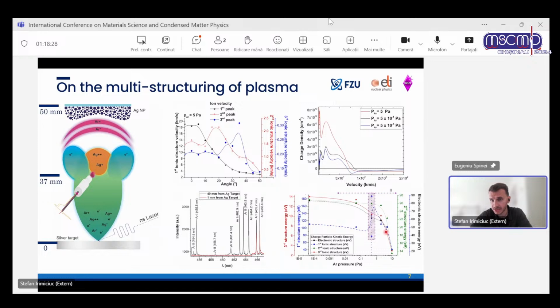We also looked at the kinetic energy, and what we found, at least for our system, is that there's a significant range of pressures, between 0.5 and 1 Pascal, where the argon, or the gas that we have in the chamber, becomes dominant and an active part of the deposition, which is something that people haven't looked at before. And when we try to paint the picture of how the silver plasma expansion in argon looks, it looks like this Mickey Mouse figure, as you can see here, which is also funny, but also tells us that we have the ionization of the argon as it goes to the substrate. So pulse by pulse, you will heat your substrate with an argon plasma,